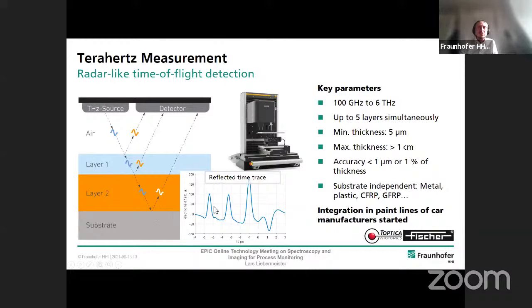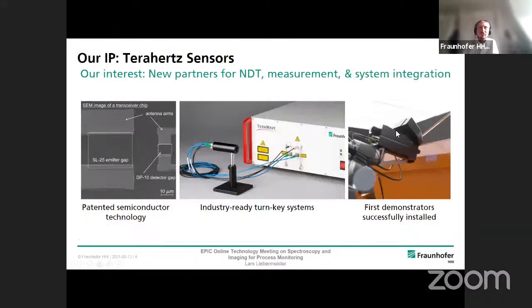And so this is where the car industry is going now to measure the thickness of the paint layers. And as Jose mentioned before, it was a project we did in collaboration with Toptica Photonics and Fischer. And one of the results was an ellipsometer-like measurement setup, which is shown here. The idea was to measure the chemical properties of the individual layers to have a characterization. But what we also did, you've seen it on the first slide, and you can see it here again on the right-hand side.